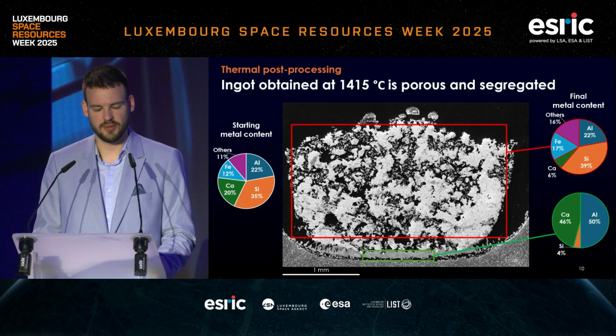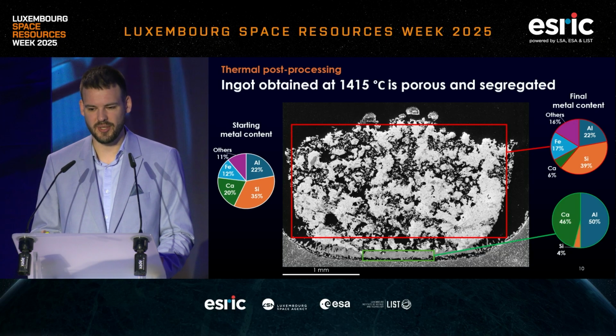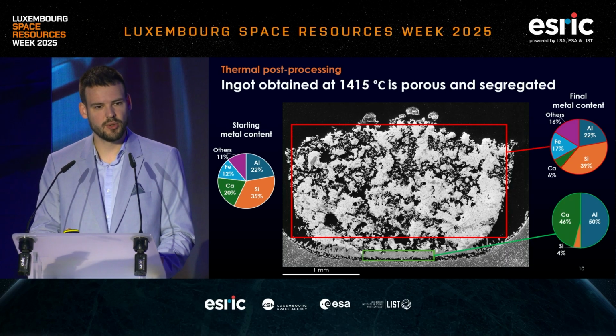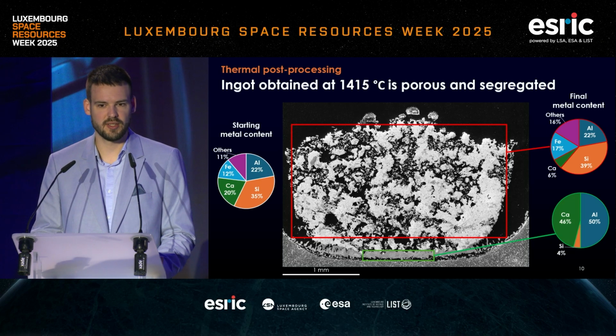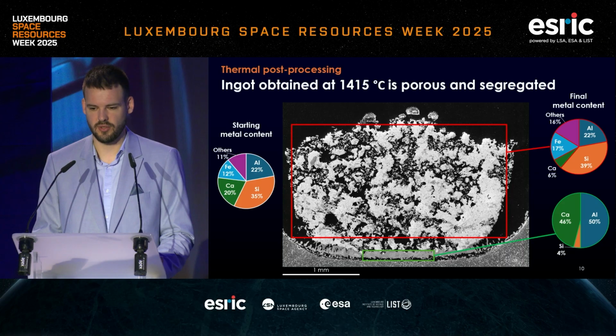Compositionally, so again on the left you have the starting composition that we measured in the material. A few interesting things in the bulk material in the red region, we see a significant decrease in calcium, which on one hand is explained by the pooling of a very calcium-rich phase at the bottom, but we also expect, at the temperatures that I'm discussing here, some significant evaporation of the calcium. I'm not going to discuss the lower temperatures that we tried, but in a nutshell, the lower you go in temperature, the less and less it is consolidated.